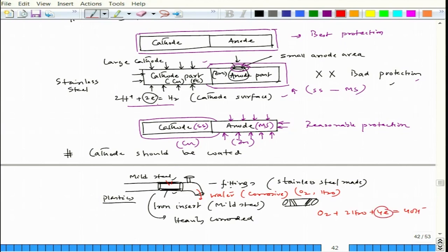In normal circumstances, the cathodic reaction is: O₂ + 2H₂O + 4e⁻ → 4OH⁻. The four electrons needed must be supplied by some anode. When the coating is intact, the stainless steel has its own protection. But the inside of the iron insert is not protected. The inside iron acts as the anode: Fe → Fe²⁺ + 2e⁻. Since this is a small section and the fitting is larger, the differential area factor comes into play — stainless steel acts as cathode, and the small insert acts as anode.